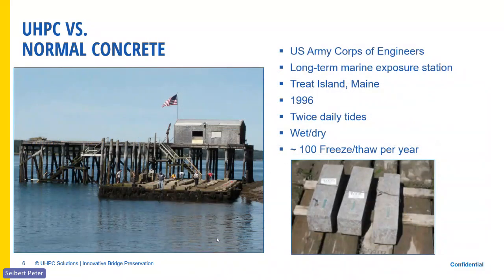So the material's actually been tested for quite some time now, since '96. This is the U.S. Army Corps. They have a long-term marine exposure station up in Treat Island, Maine. On this wharf, you put a whole bunch of concrete samples, and you get about 100 freeze-thaw cycles a year. If you put a non-air entrained concrete in there, it's going to be deteriorated and gone within a year.